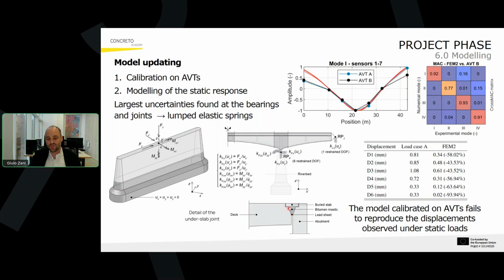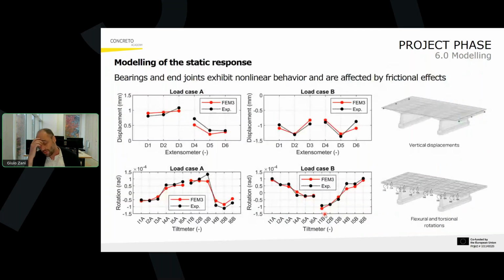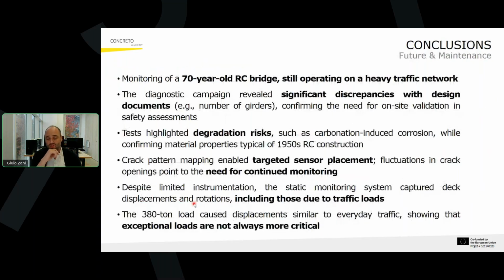These are very complicated joints with some bitumen mastic, a buried slab, and then a set of technical layers above the joint as well. This is important because only after a further calibration of the static model were we able to obtain a good agreement between the numerical results and the experimental measurements that we carried out during the passage of these trucks. I will now proceed with some conclusions because the time is almost over.